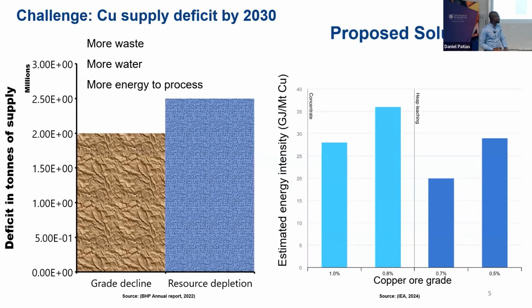So heap leaching, because if you look at the graph on your right, and you consider your estimated energy intensity against your copper grade. So if you take low grade, or 0.7% copper head grade, you're using almost 20 gigajoules per ton of copper, as against, in a similar vein, 0.8%, and you're finally crushing it to get concentrate, floating it, and probably leaching it thereafter, you need almost double the amount of energy in that respect. So heap leaching, it's really good in terms of energy usage and in terms of us getting copper to meet the growing energy demand.